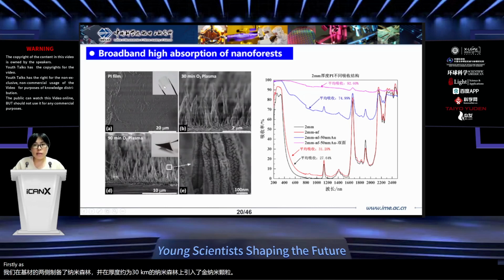Firstly, as visible to the naked eye, the flexible transparent substrate became a flexible ultra-black substrate. And within the wavelength range from 200 to 2400 nanometers, the average absorption increased from the initial 27% to 92%, achieving a wide band high absorption.